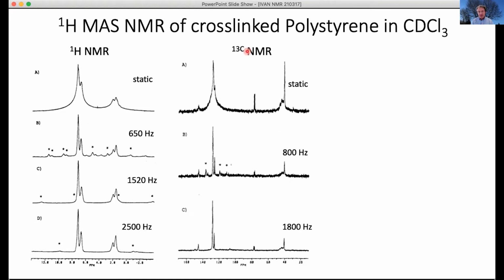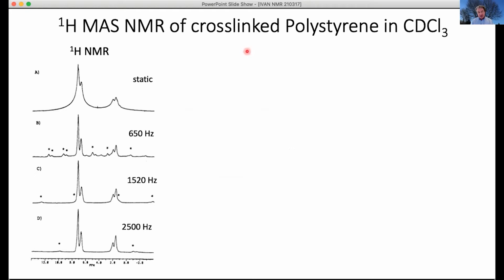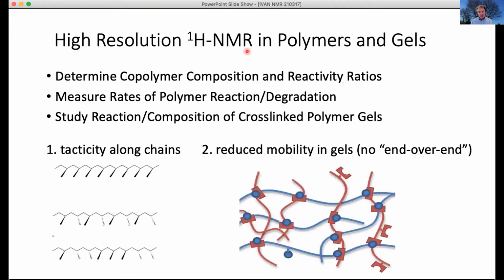Magic angle spinning of a gel provides, with swollen gels, most of the averaging from segmental motion of these chains. The end-over-end motion is just not available on the NMR scale, so a little bit of magic angle spinning will collapse the broadening due to that.